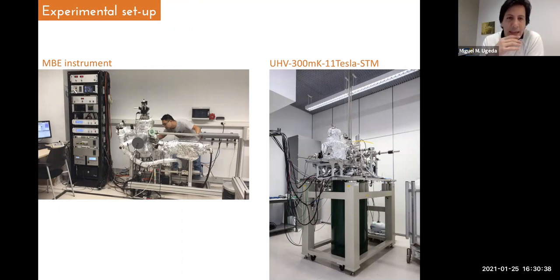So this is our experimental setup in our lab. We have an MBE instrument, a molecular beam epitaxy instrument that you see here. Here is the place where we grow our 2D materials on different substrates, for example, on graphite or graphene substrates, many different substrates. And by the way, we only use this MBE system for selenium-based materials in order to avoid cross-contamination with, let's say, sulfur or tellurium-based materials. So we only use this for selenium-based TMD materials.